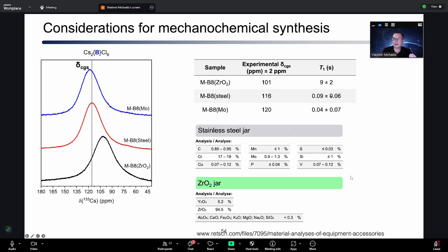Okay. What that tells you is you're still stripping a paramagnetic ion out of this. Because stainless steel has chromium and iron and molybdenum, or manganese, in a paramagnetic system, you still etch metals from that. And we confirmed that looking at molybdenum. So we made a molybdenum one, and again, you can see that the T1s are on the same order. So molybdenum is paramagnetic here. The iron, the chromium, and manganese are paramagnetic here. You are getting some etching as well in the stainless steel.